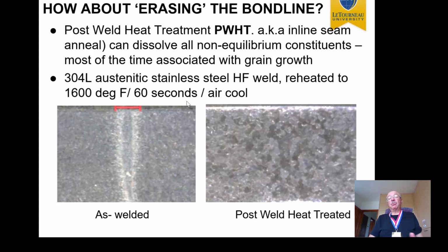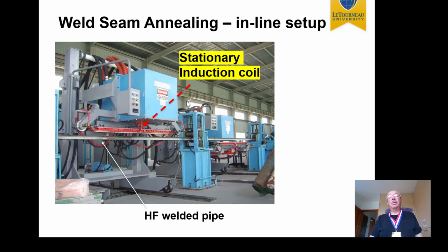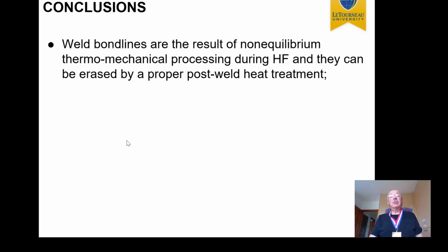It is just a different microstructure, though you end up paying some price by having grain coarsening in this case and probably lower toughness, but this was austenitic stainless steel. I don't think toughness was a concern. So it can be costly to do this kind of post-weld heat treatment in line. You can see here the welded pipe has to run under an induction coil. You have to make sure that the weld is not squeezed or skewed from the induction coil. There are certain complications with this. But if you're bothered by bond lines, by golly, erase them. That's my point. So, in conclusion, we concluded that bond lines are the result of non-equilibrium thermomechanical processing